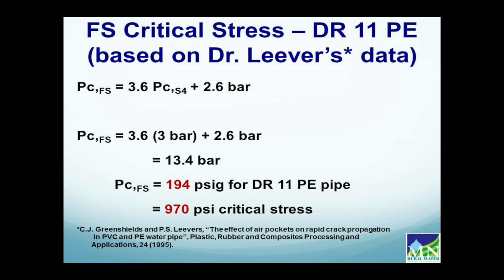So this is the critical pressure that we'll use, in this case 3 bar. This is the correlation equation that we talked about. The full-scale critical pressure is 3.6 times 3 bar plus 2.6, which is 13 bar. Multiplying that by 15, we get to about 195 psig. That's the critical pressure for this DR11 polyethylene pipe.